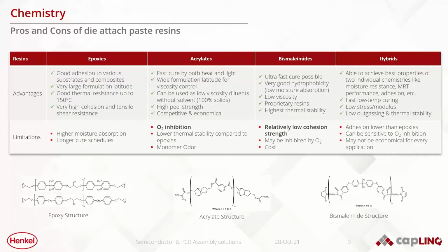But acrylates, for example, might allow the material to cure much more quickly with UV light, but they do have some oxygen inhibition. Bismaleimides, on the other hand, have very good hydrophobicity, which means that they repel water, which makes up for a much lower water absorption. However, bismaleimides have low cohesion strength, which means that they don't have much adhesion to themselves. This is where the hybrids come in. Hybrids mix and match some of these chemistries together in order to make the strong points of the chemistry stronger, while making the weaker points of the chemistry less important.